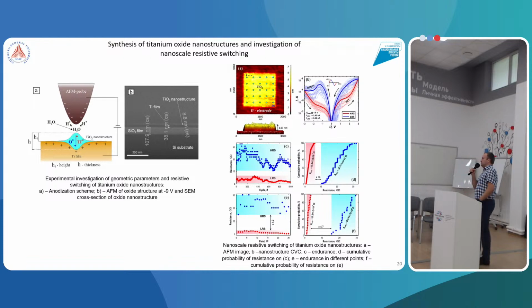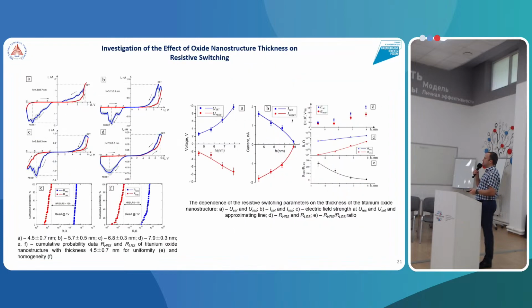We use nanoscale methods to investigate the synthesis process of titanium oxide materials and the investigation of nanoscale resistive switching. Here we present the formation of oxide nanostructures of titanium dioxide, and on the right side we measure the nanoscale resistive switching stability, endurance, and present the distribution of cumulative probability.